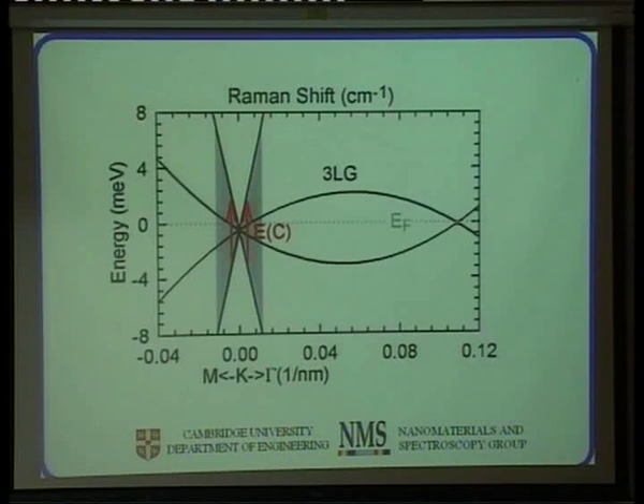close to the Dirac point, while the G peak and so on is about 200 milli-electron volts, so it's very far from there. So we think there is a Fano interference there between this low energy electronic transition and this Raman mode. And of course, we discussed about the 2-layer and the bulk.